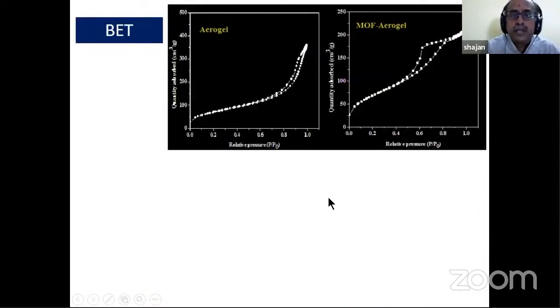Now you can check the surface area as well as the BET isotherms. This is the BET isotherm for the aerogel, and when we add the MOF, you can see there is a difference. These are nitrogen adsorption-desorption studies. You can see here that it becomes more robust, more strong. This is an indication.